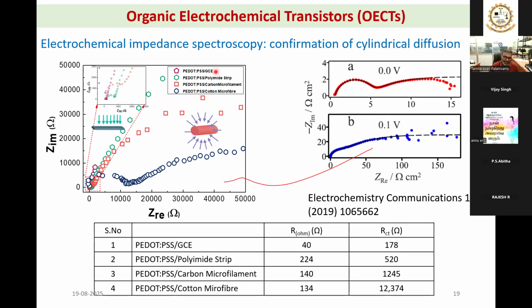Say, if you take a simple glassy carbon with PEDOT:PSS, you can see it is pretty much parallel to your imaginary axis. Something parallel to the imaginary axis means that it is a double layer property. And here also, if you take another one, a polyimide strip, once again it is a strip, like a planar structure. So you have a diffusion region pretty much close to your imaginary axis. And if you take a carbon microfilament with PEDOT:PSS, which is a well-known conducting filament, you are seeing once again the saturation kind of profile. So this tells us whenever you use any cylindrical or microfiber electrode, you are actually getting the cylindrical diffusion. Okay, so now we proved that we can achieve the cylindrical diffusion, and we wanted to use it in our device.